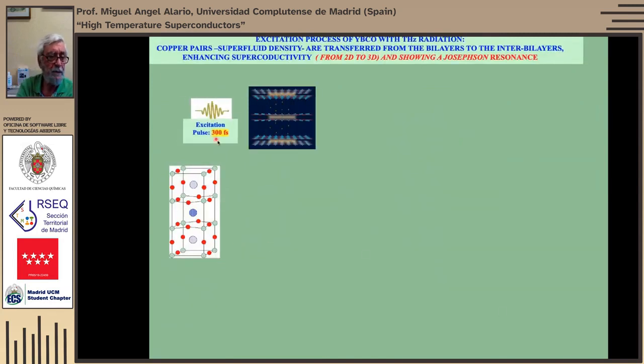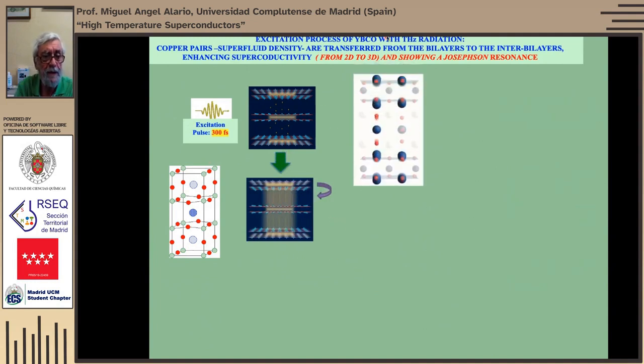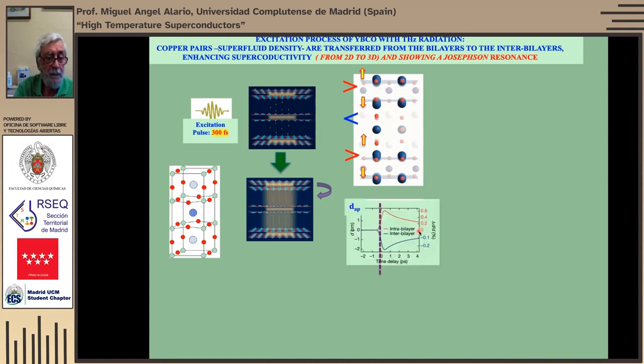So you said 300 femtoseconds, very, very brief. So what happens then? You get change in the structure. This change in the structure is the following. This is the same as we have seen before. So this, which is the bilayer, increases, and this, which is the interlayer, decreases. So it means that you are transferring current from here to here. So this is less strong, and this is more strong. So, in fact, if you measure now with the X-ray diffraction, this machine in California, then you see that the intrabilayer goes up and the interbilayer goes down. So this increases and this decreases.